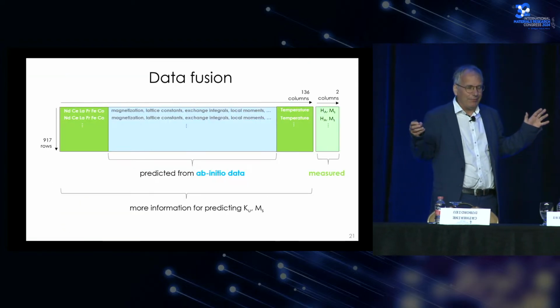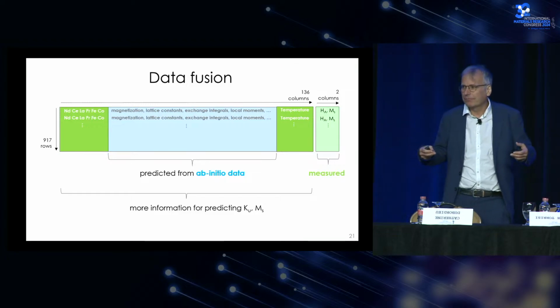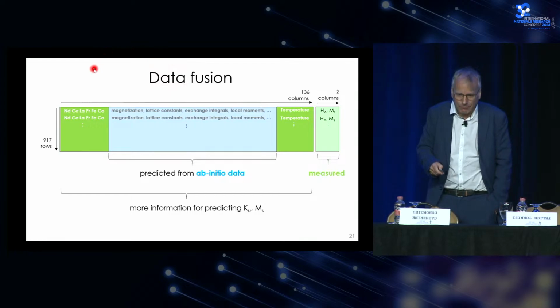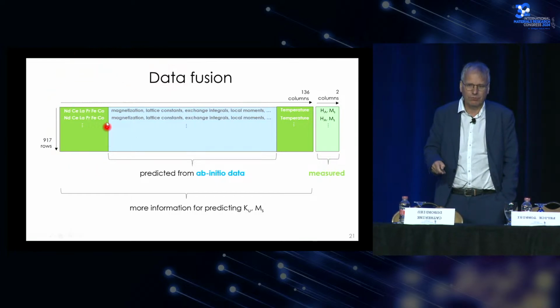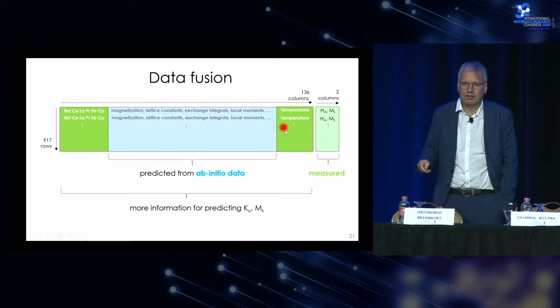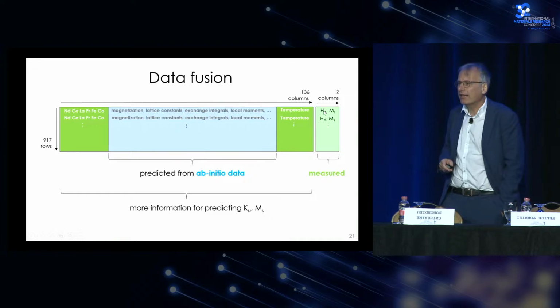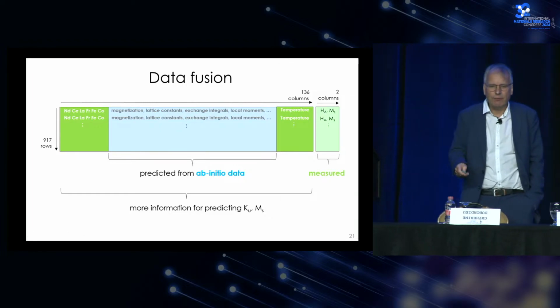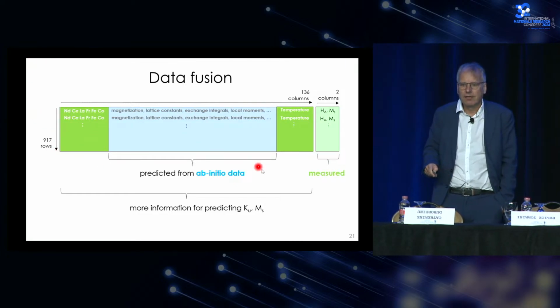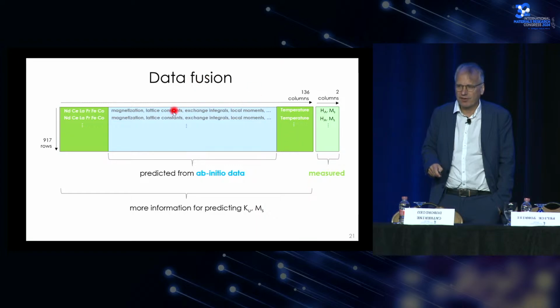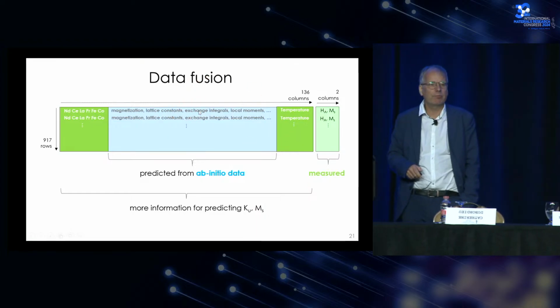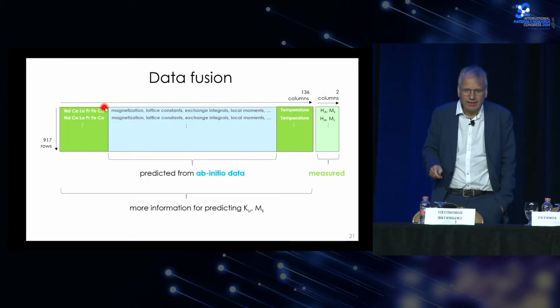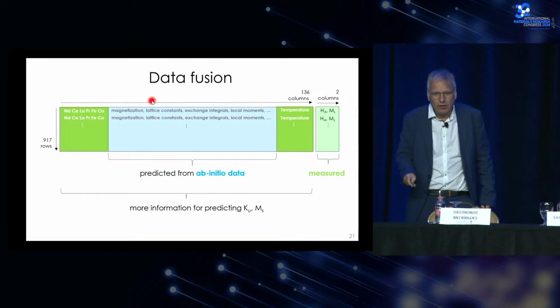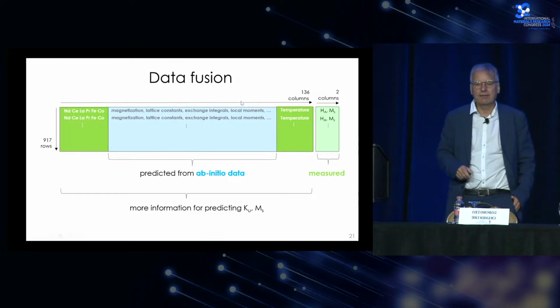So one thing we always have to do is gather all the data we have. In our case, we had magnetic measurements: given a chemical composition, measured at a certain temperature, we have the anisotropy fields and the magnetization measured. We realized that we can do much better predictions if we augment our experimental data with a data set coming from first principle simulations. In the first principle simulations, our friends at Tokyo University can compute the magnetization, the lattice constant, local magnetic moments, exchange integrals.